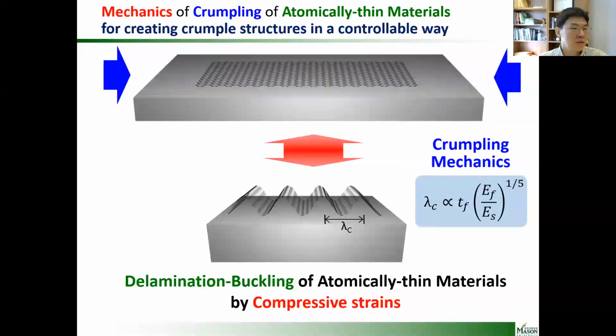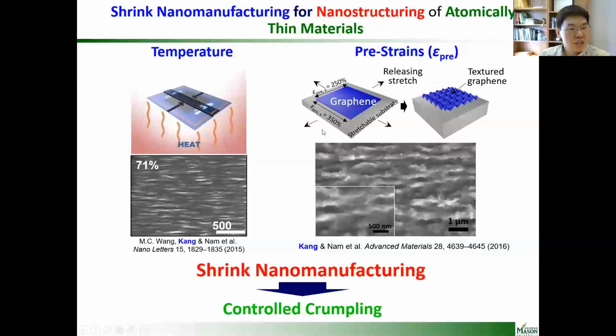After we synthesize materials, as I mentioned, we create nanostructures using a simple technique called shrink nanomanufacturing. We can create nano or micro structures using this shrinking technique. Here, first you can imagine we transfer the graphene onto a flexible substrate, and first we stretch the substrate and then transfer. As we release the stretching, we get wrinkles in the atomically thin sheet of graphene, and that way we can create these small nano or micro scale wrinkles, and this is how it looks. So as we use this shrinking nanomanufacturing technique, we can controllably create the crumpled structures.